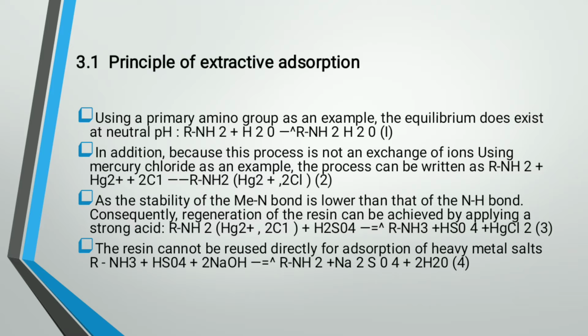As the stability of the Me-nitrogen bond is lower than that of the nitrogen-hydrogen bond, consequently the regeneration of the resin can be achieved by applying a strong acid. The resin cannot be reused directly for adsorption of heavy metal salts. You can check the equations for adsorption for the given metals in the equations above.